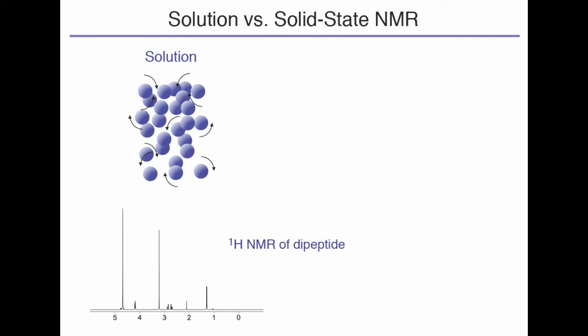So if we imagine what happens in a solution, you have rapid molecular tumbling of all of your species, and what that does is it actually averages out any directional interactions, which we call orientational interactions. So it removes them, meaning that you get these very nice sharp peaks.